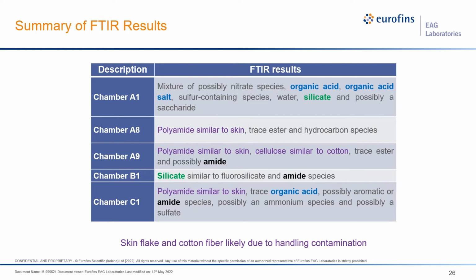Now, in chamber C1, we also saw a trace organic acid. That could be very problematic for electronics. And then the amide, ammonium, that could also be quite problematic. So overall, with respect to FTIR, we saw that chamber A1 as well as C1 were quite contaminated. And the ones that are sort of purple, those ones are probably just some kind of handling contamination. So we would consider. And now I believe the next part is XPS. So I will turn it back over to you, Dan.